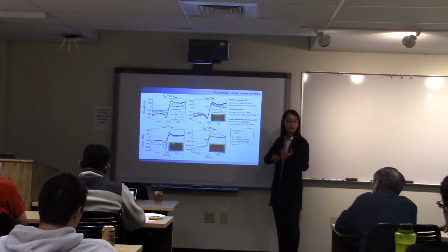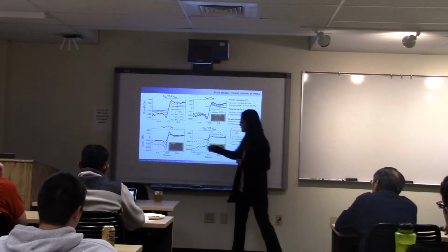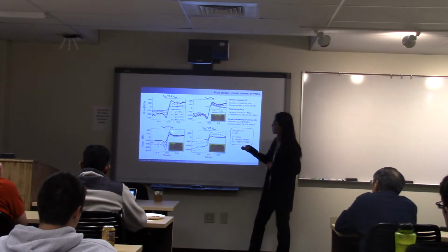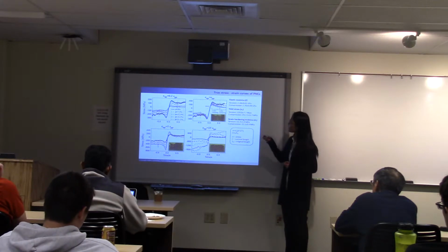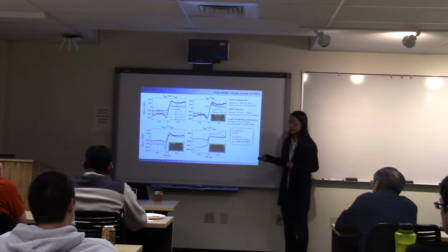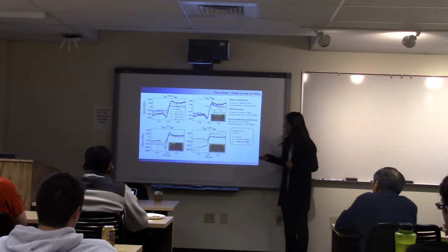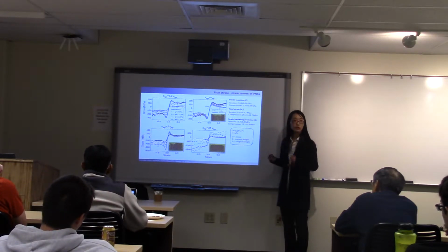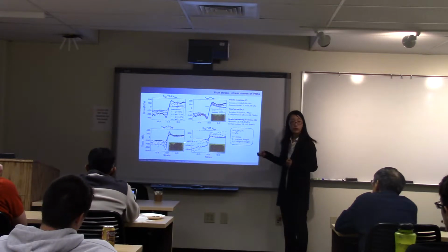And here, when we further increase the nanoparticle-polymer interaction strength, we first find the reinforcement in the compressive domain. But in the tensile domain, we only find it in the elastic part. But in the plastic part, the original strain hardening is replaced by strain softening. Also combined with the snapshot, we could imagine that this localized deformation could possibly contribute to the strain softening happening here.